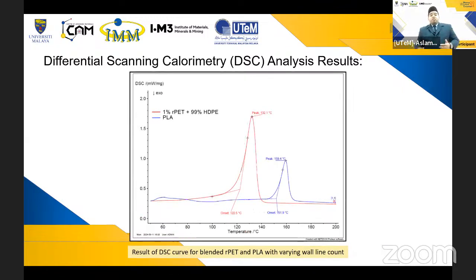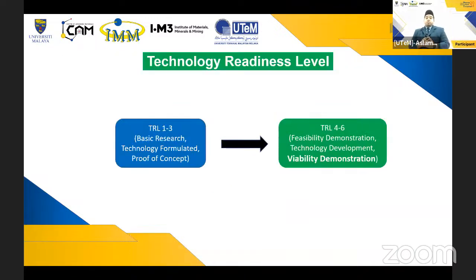So below shows the result of the differential scanning calorimetry analysis. It shows that the blended rPET exhibits a lower melting point compared to the PLA. With the lower melting point, we can use it for 3D printing applications much more easily and much more quickly.